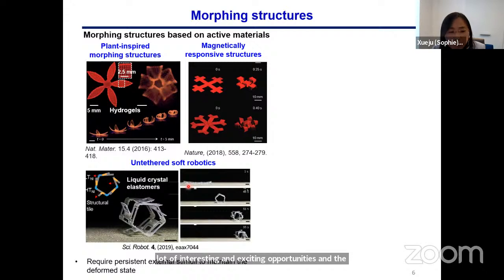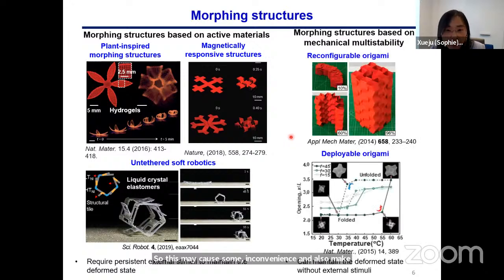One potential limitation is that they require persistent external stimuli to maintain the deformed state. For example, for the magnetic composite structures, when we remove the magnetic field, the structures will return to the original shape. So this may cause some inconvenience and also make it less energy efficient for some applications.